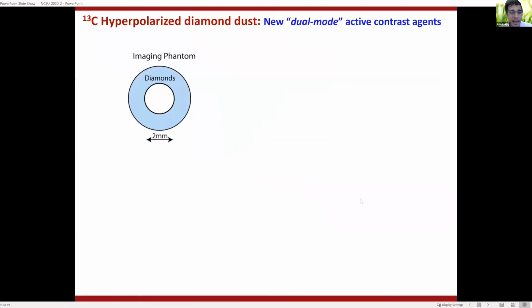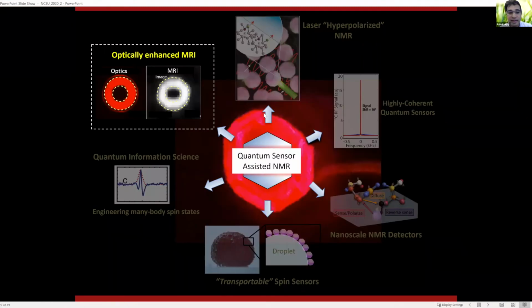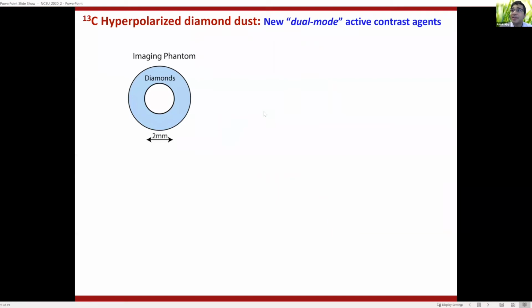The simplest application is in MRI, and it's quite obvious because MRI is an imaging version of NMR, and because these spins are very bright in optics, bright in NMR, you can also make them bright in MRI. So here's a very simple proof of concept experiment. We have a ring, and we filled this ring with diamond particles. This is one of the good things about diamond particles. They fill whatever volume you want them to fill.